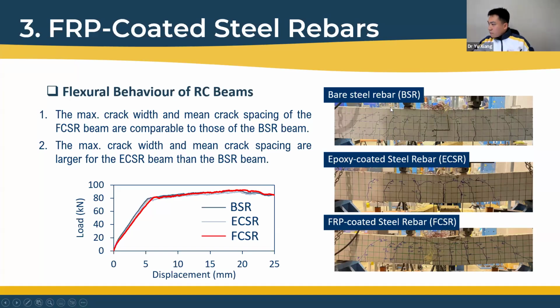More importantly, from the crack patterns, we find that the crack number and crack spacing for the beam reinforced with FRP-coated steel rebar is generally the same as the beam reinforced with bare steel rebar. But for the epoxy-coated steel rebar, just as expected, the number of cracks was much lower than the other two beams, the spacing of cracks much larger, and the crack width a little bit wider than the other two beams.